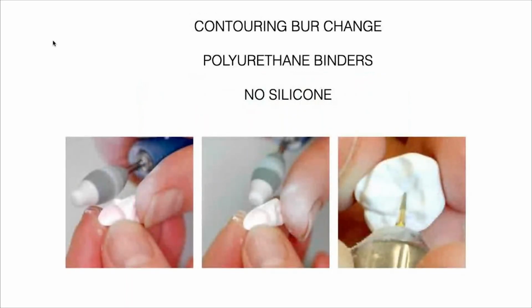So you see what they do is they use the green stage first to knock it down, and then they switch to the white part. I find that very uncomfortable. The only good thing is that they don't have silicone binders because that can be detrimental to the zirconia. So you need to use polyurethane binders. And if not, you're going to get all kinds of discoloration.